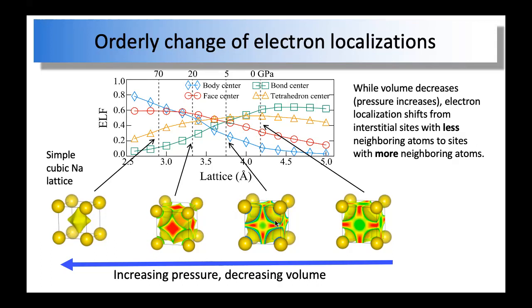And another very interesting feature is that when you compress this from this length further down here, the electron maximum actually moves, and it's very fun to see. The maximum actually shifts for sodium, not for all the atoms, but for alkali atoms, alkaline atoms, they all show this feature. It shifts from the bond center, or from the edge center, to the face center. And at a particular point, of course, for sodium it is exactly at 5 GPa.